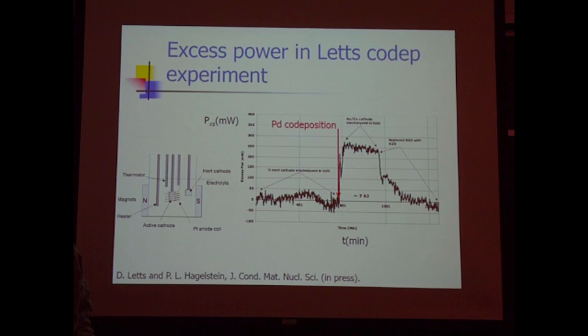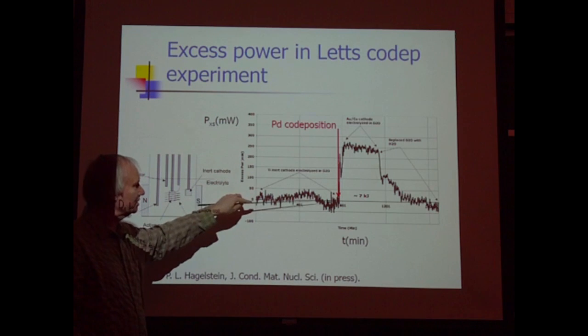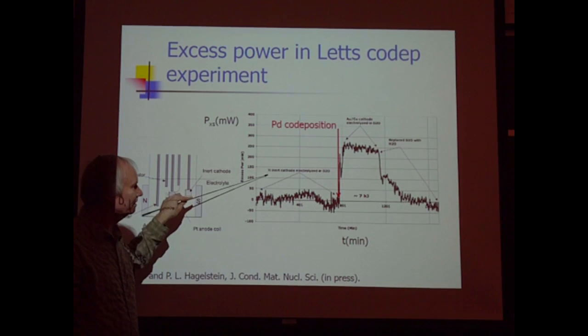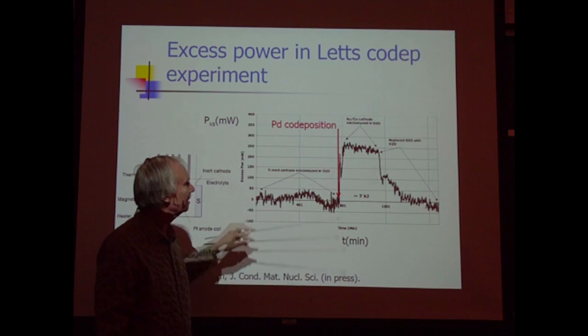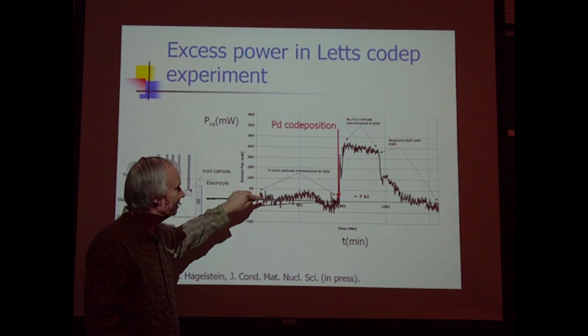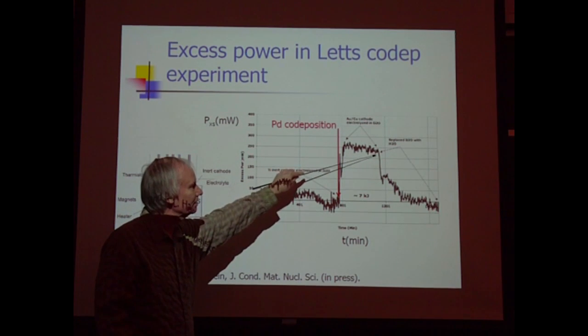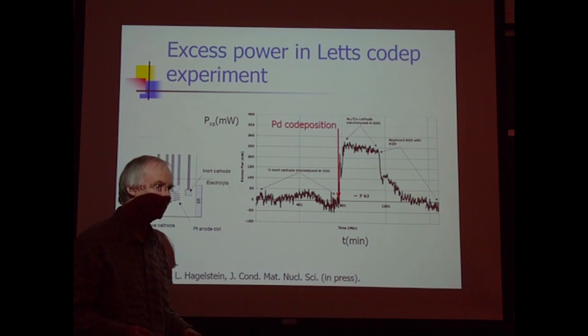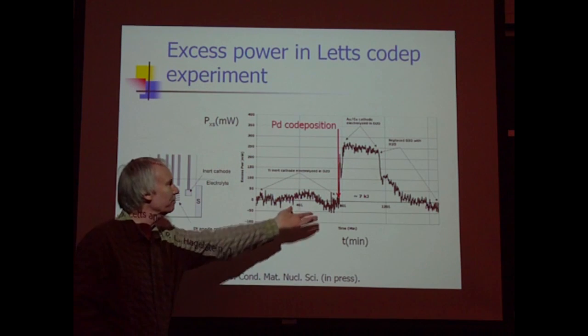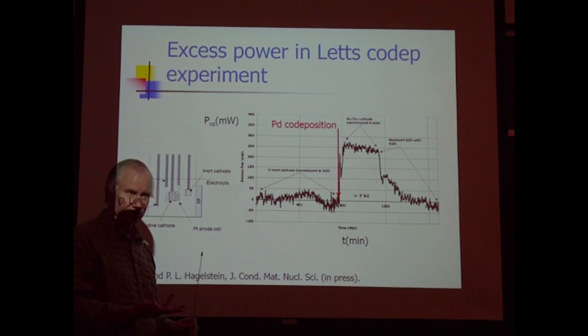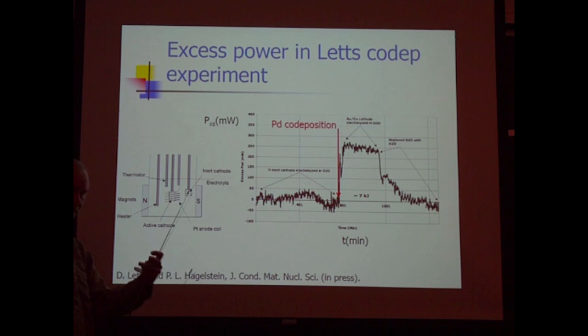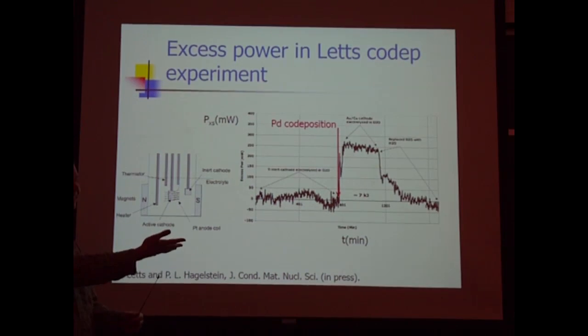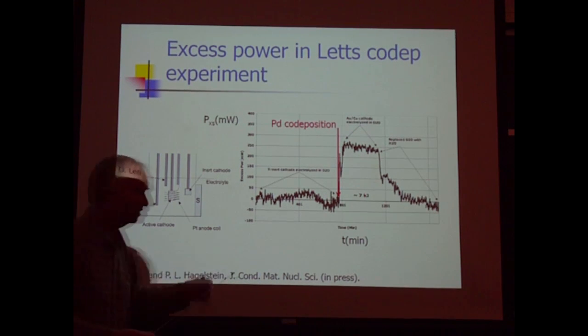So then he said, well, what do you have to do to get it to adhere? And what he said is, well, let's co-deposit more slowly, so you reduce the concentration of palladium in the electrolyte by 25 or so, and co-deposit at high current density. And as soon as he did that, he saw data something like this. So you co-deposit, in this case, palladium, which I think was a separate, co-deposited on a copper cathode coated with gold. Palladium co-deposition occurred, excess heat turns on promptly. Here he replaces the heavy water with light water, and the excess heat goes away. But if you like, this shows that the excess heat supports the notion, namely co-deposit palladium at high current density, make the vacancies, excess heat, short time, don't have to wait a month, 6 weeks, and there you have it.